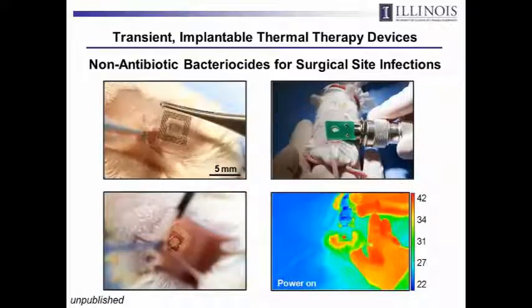If you look at iron or tungsten, to some extent zinc, it's much messier because they form oxides that then dissolve at completely different rates than the native metal. And so you get flakes, you get porosity that develops as it's dissolving. For an implantable system, you don't want the thing to be fragmenting apart as it's dissolving, because then you get suspended chunks of stuff that could get into the bloodstream, for example, and cause big problems. So it goes beyond just the biocompatibility of the materials themselves and their capacity for dissolving in biofluids, but it's really the nature of that dissolution and how it's disappearing that becomes a really important consideration as well. So if you use all of those filters, right now molybdenum and magnesium look like the most attractive candidates.